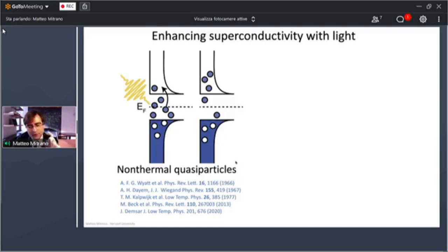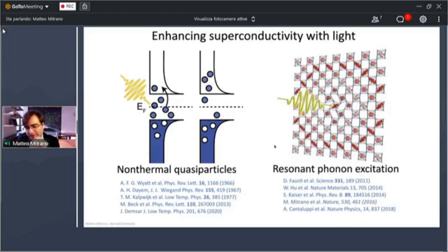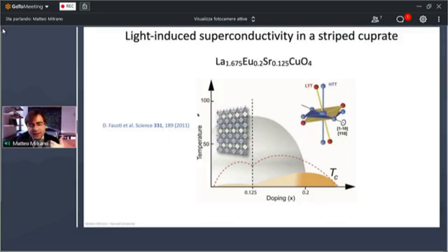More recent work has raised the critical temperature for these transitions that are typically found at very low transition temperatures. More recently, the group where I got my PhD, led by Andrea Cavalleri, started investigating whether resonantly exciting certain vibrations of materials and deforming the structure of materials could lead to optimized superconductivity. One pioneering experiment that was performed in 2011 by Daniele Fausti and Andrea Cavalleri was that in a particular cuprate, it was possible to use laser pulses resonantly tuned with a distortion of the lattice, with a vibration of the lattice that corresponds to a distortion,